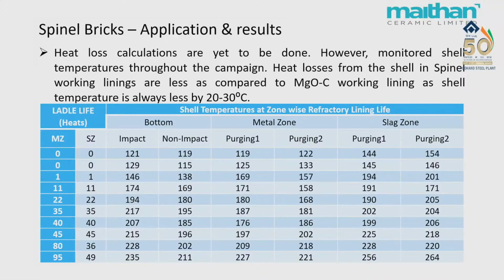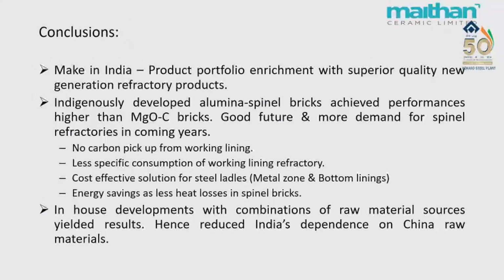Heat loss calculations are yet to be done, so we have not yet completed that. But we have monitored the shell temperatures throughout the campaign, and it is clear cut. We can see a 20 to 30 degree shell temperature difference between the spinel area and the MgO-C area. Energy saving aspect of spinels.